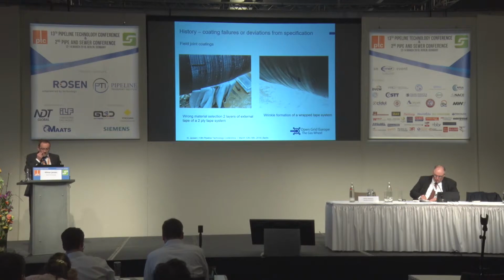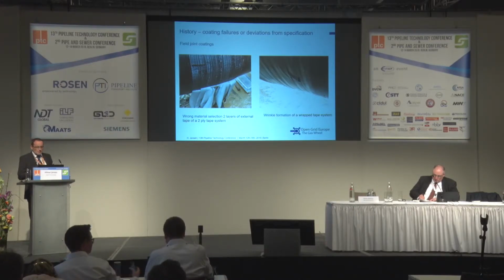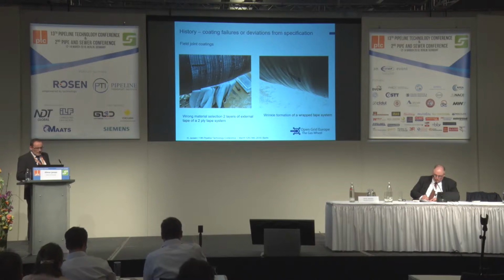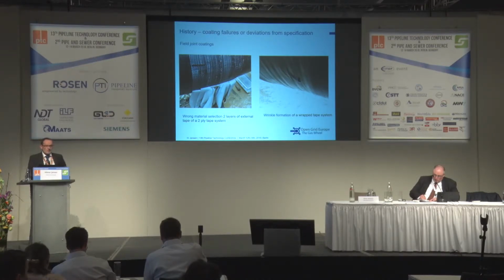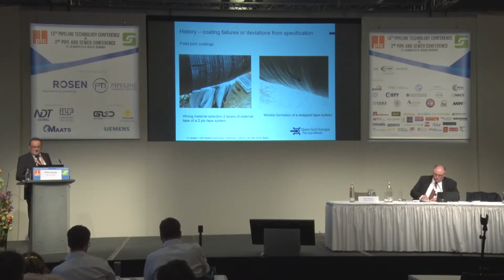On the right photo, you see a wrinkle formation of a tape system. This wrinkle may occur if you choose the wrong tension of the wrapping machine. If the tension is too small, you may create such wrinkles, and in the worst case scenario water may penetrate through this wrinkle and reach the steel surface, and due to the shielding effects on cathodic protection, corrosion may occur beneath this field joint coating area.